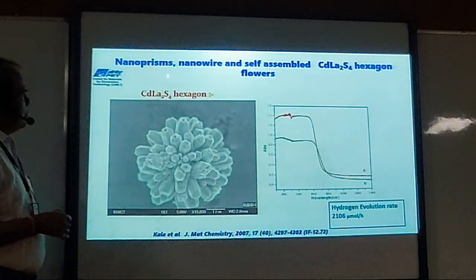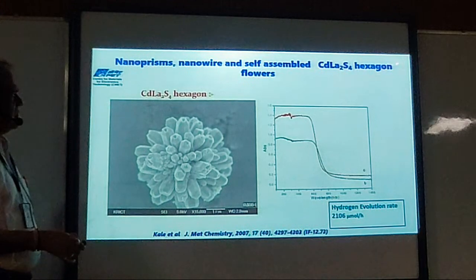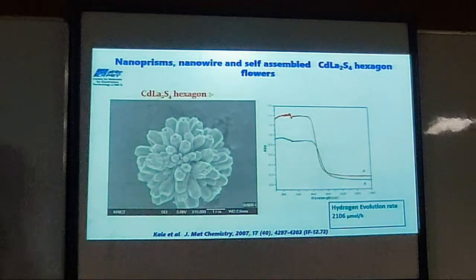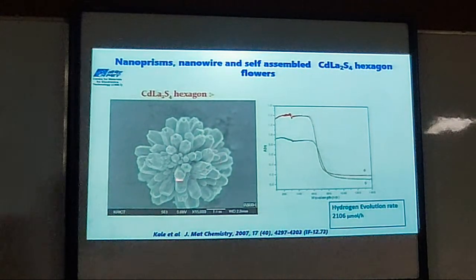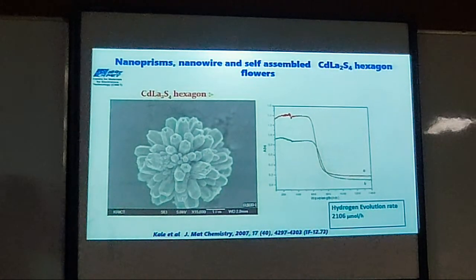You see the nanoprisms, nanowires, and self-assembled cadmium lanthanum sulfide. What is the beauty of this structure? You see all the hexagonal cells assembled into one, and they are highly porous and highly crystalline. Because of this, their band gap is in the well visible region. See, the absorption is within the visible region, so it shows good photocatalytic activity.